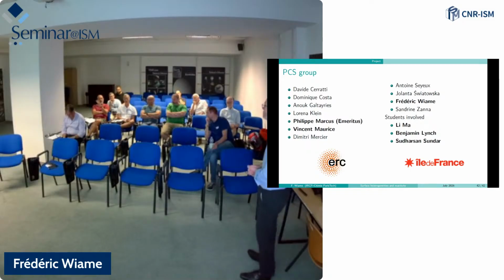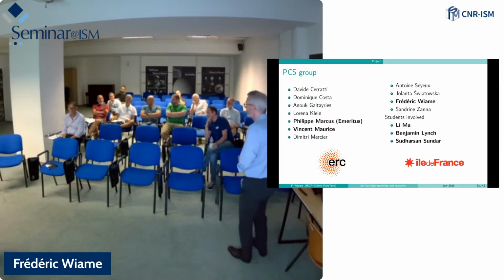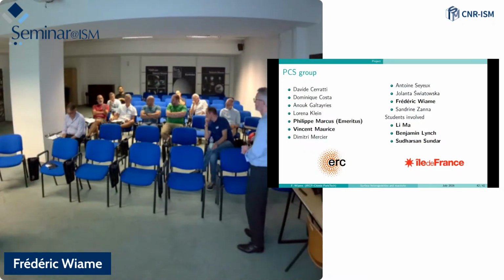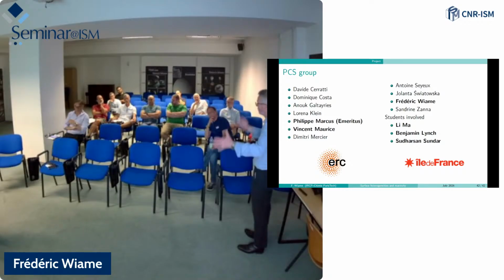Okay, but sorry, just one last thing. The atoms that you have after sputter annealing on the surface, that you get the root 2 by root 2, these are chromium, you said, or it can be chromium, iron. After annealing, so before annealing, we have iron, chromium, nickel. To have the reconstruction, we obviously need to anneal, and then we have iron, chromium, and nickel.